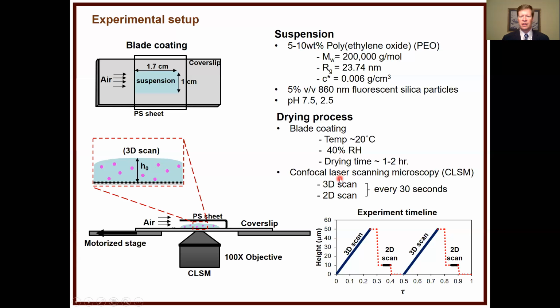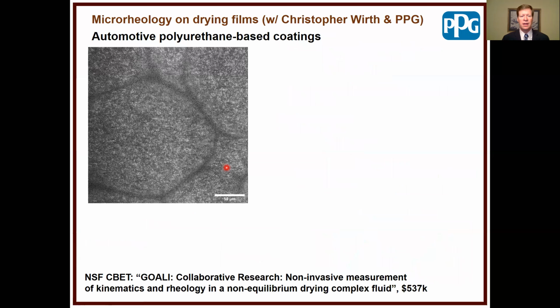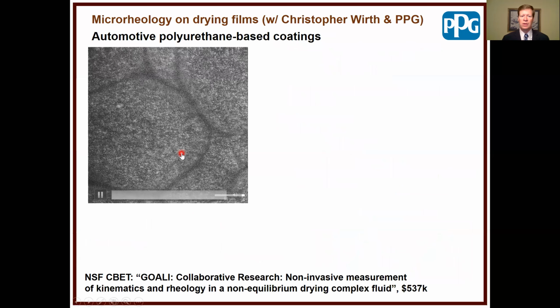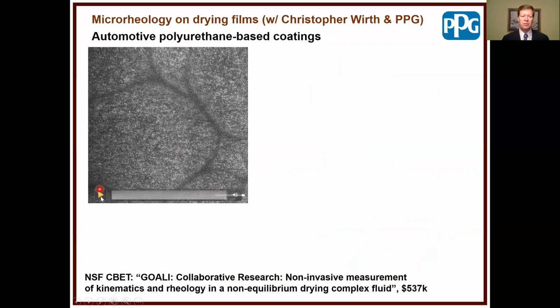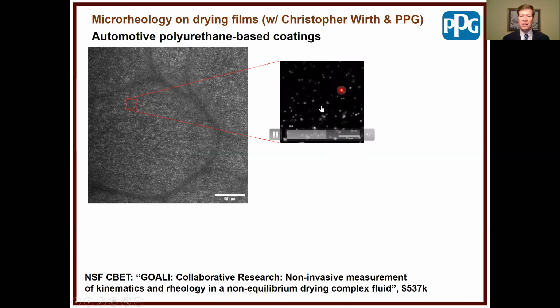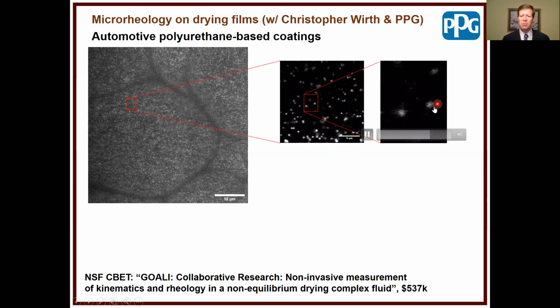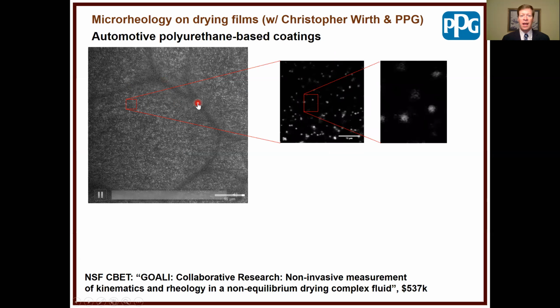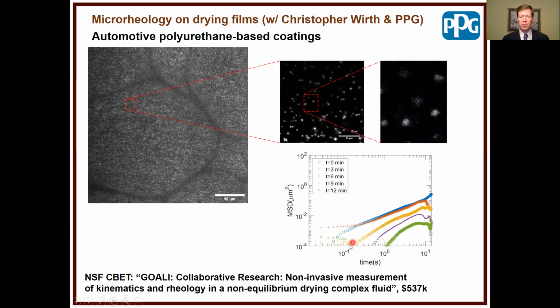And then we're going to use laser scanning confocal microscopy to scan through the system. And what that allows us to do is optical sectioning at different levels. Or what we can do is just scan at a certain height and do microrheology. So today I'll talk less about microrheology, but at the talk we had yesterday, and if you have questions about this, I just wanted to highlight, even when you have a very complex flow, as long as you can see particles on the inside while you're flowing, what you can do is determine the local velocity, of course, from PIV, but then you can zoom in even more to individual particle trajectories and back out this complicated motion and get the Brownian motion, just to give you the ability to do microrheology.